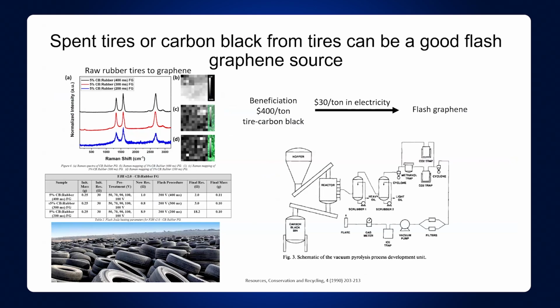So one of the sources we can use are rubber tires. And remember I told you these rubber tires are a big problem. They do treat rubber tires, and they can bring them back. They can thermalize them, and they bring them back to the carbon black, because about 30% of the weight of your tire in your car is carbon black. It's just a carbon sooty material that's made by the pyrolysis of methane.